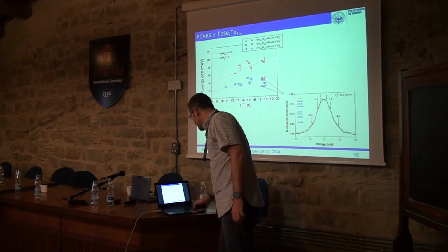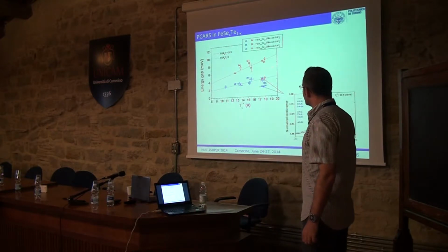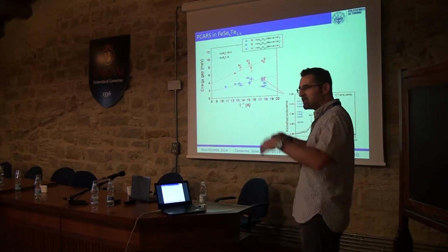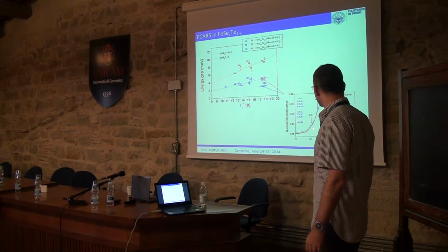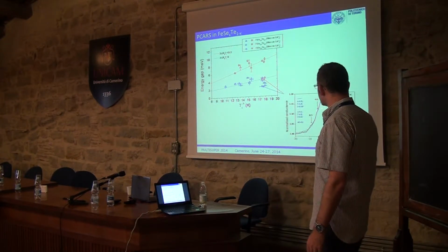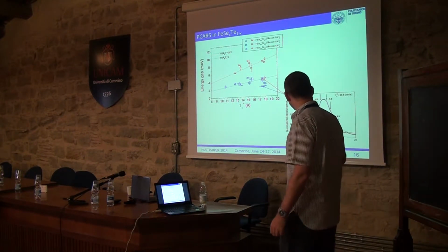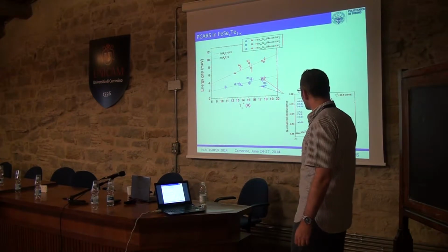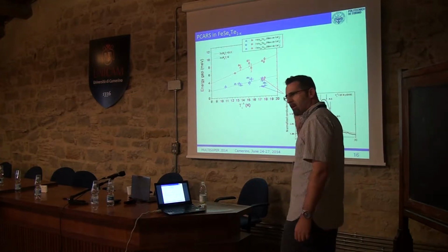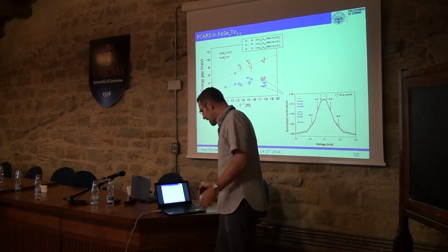This simply means that in some curves, we do not have a very big structure associated with the electron-boson coupling, but we still have very clear structures associated with the two gaps. So it's possible to fit the curve with two gaps, one here and one there. Well, this is complicated. Then what is the real gap?